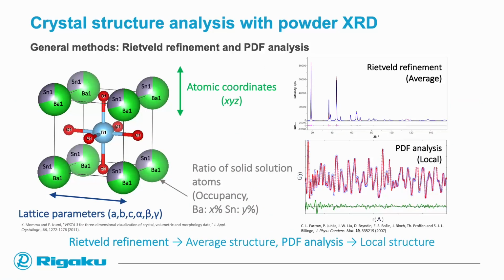When it comes to the deeper understanding of the crystal structure, with the use of powder XRD, we can choose between two similar methods. One is the Rietveld refinement and the other one is the pair distribution function analysis. Both rely on the powder pattern of our material, but the PDF analysis utilizes the whole powder pattern range. So it requires a larger Q space compared to the Rietveld refinement, which only relies on the Bragg information, the reflexes. However, from Rietveld refinement, we can draw information about the average structure, about the long-range order of our atoms, about the crystal structure. So, for example, lattice parameters, but also about the atomic coordinates and also the occupancy level of our cations, for example.